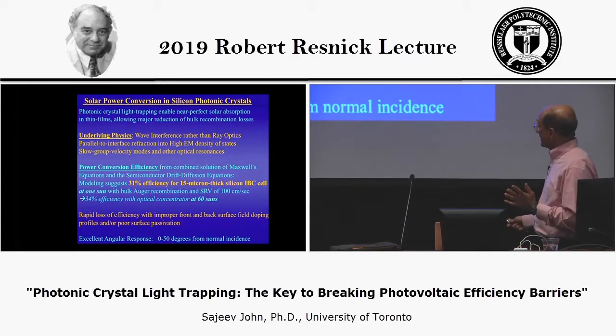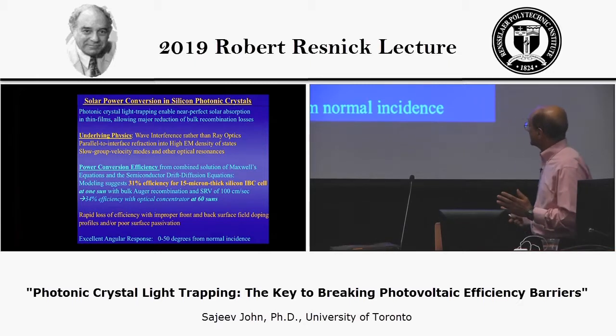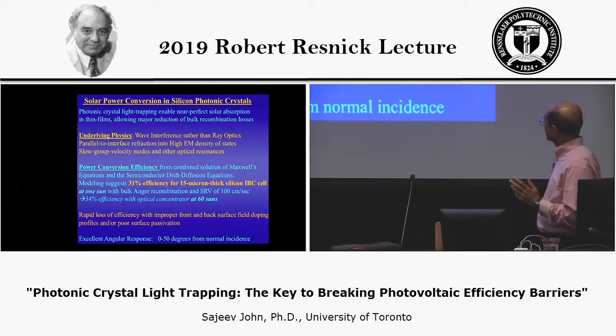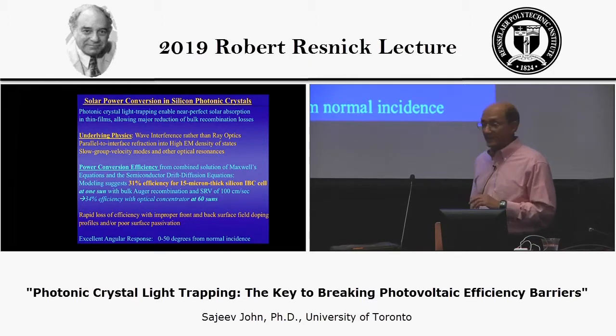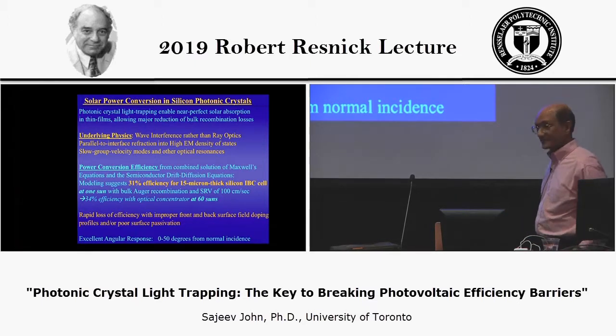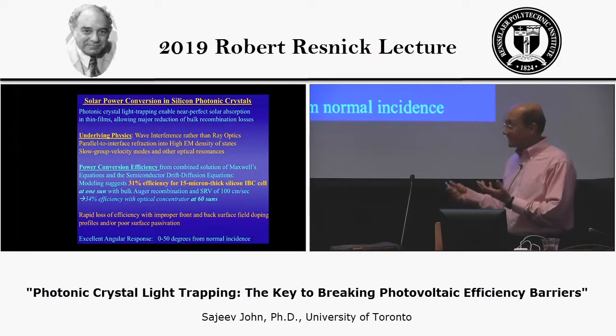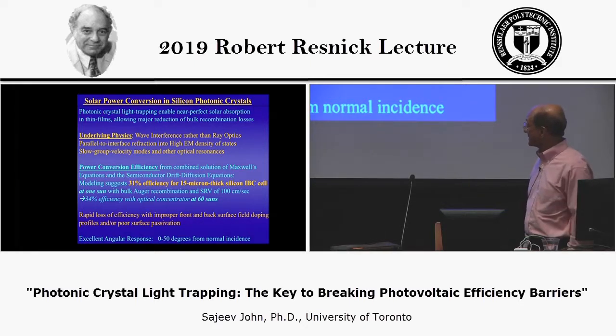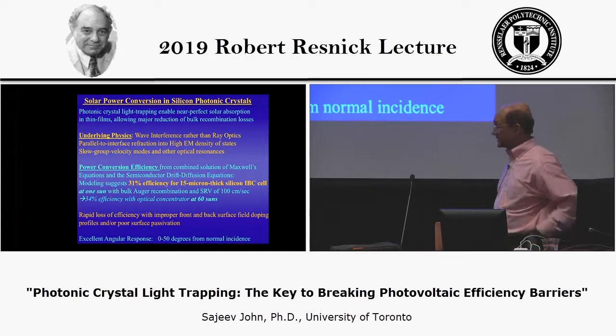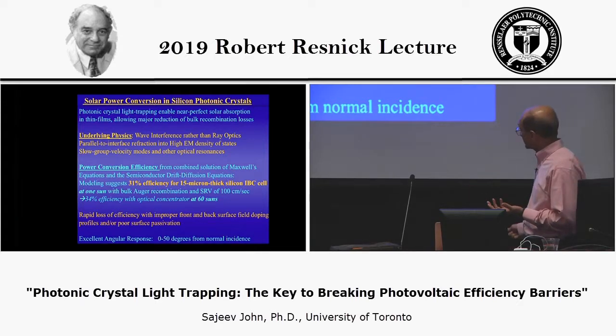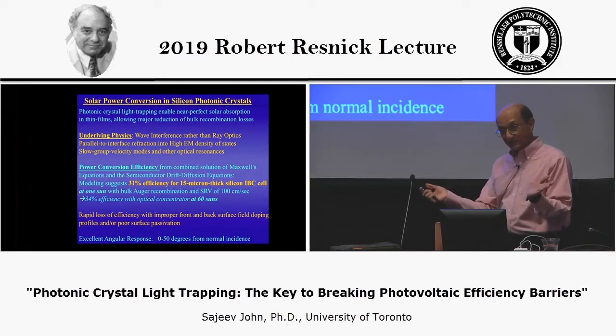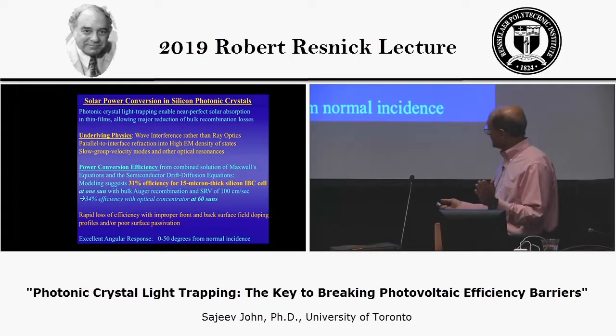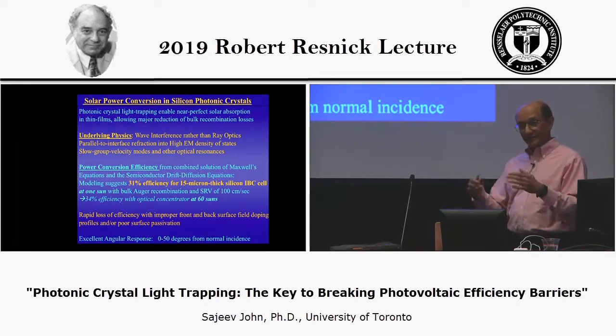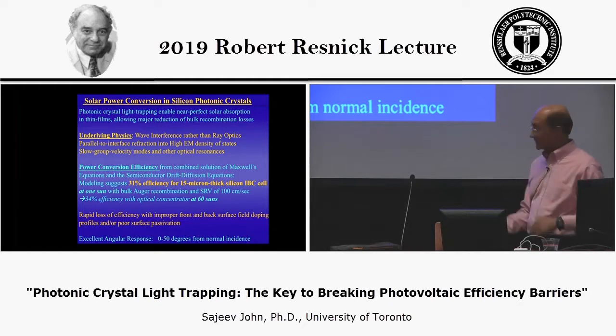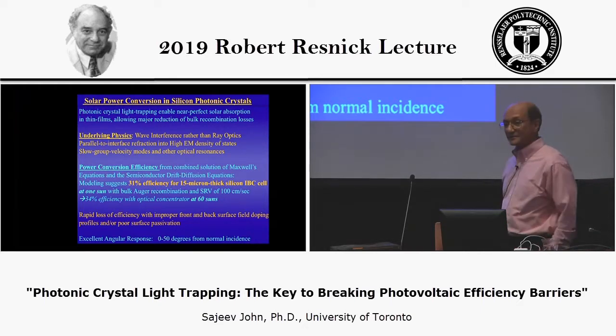And finally, there's a rapid loss of efficiency if you don't have the right front and back surface fields and doping profiles, and/or poor surface passivation. So the challenge is to combine both the best optical structures with the state-of-the-art electronics. And finally, these structures, due to their photonic crystal architectures, have very good angular response up to about 50 degrees off normal incident sunlight, which is very valuable if you don't want to be tracking the sun throughout with your solar cell device. So let me just stop there.